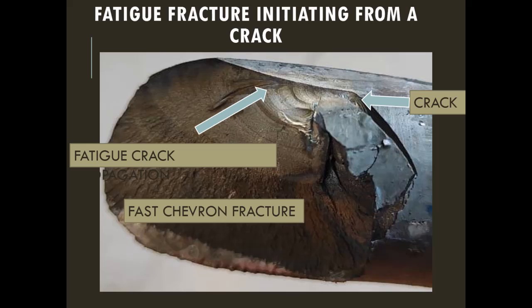This is a case of fatigue fracture initiated from an unnoticed crack on the spring. This crack initiated a fatigue crack of very high magnitude, and the rest of the surface shows a fast chevron pattern. Normally in springs, surface integrity is very important — the surface must be free of any cracks, surface blemishes, or manufacturing defects like laps or seams.